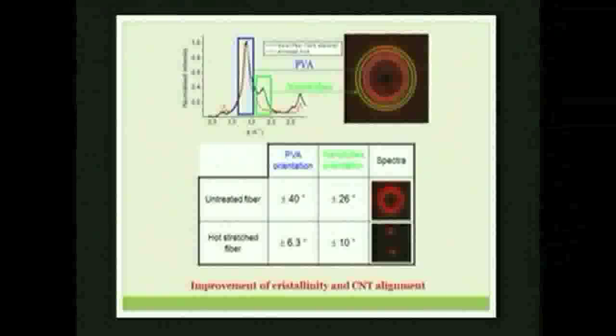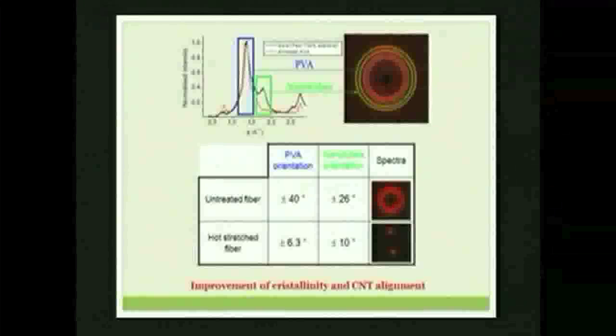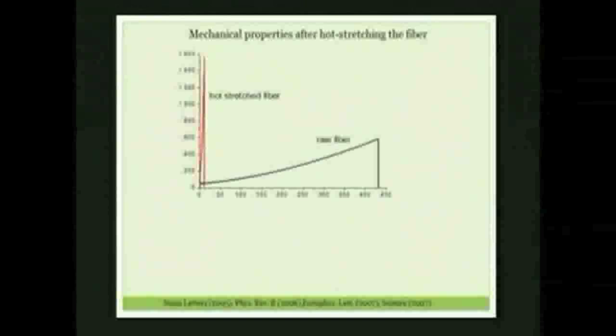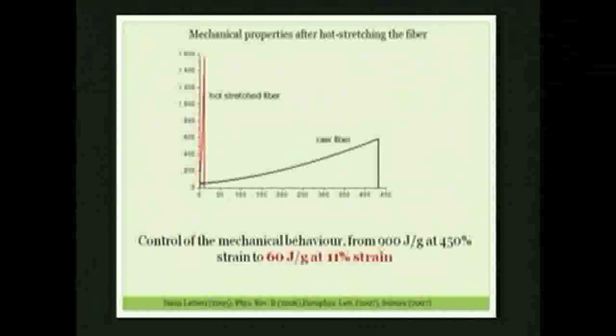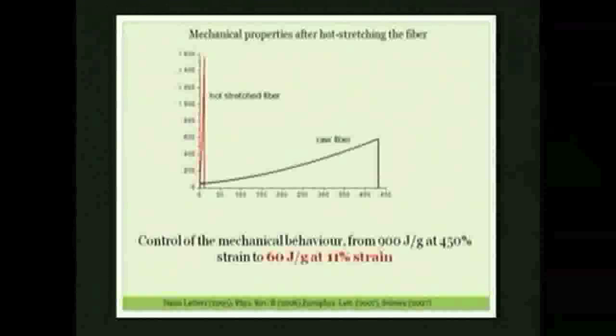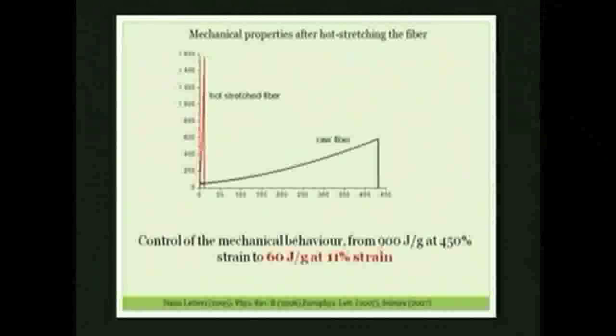And we also see that the crystallization of the polymer is improved by the heating process. And this led to completely different mechanical properties than before. This is the raw fiber that I've shown before, and this is the same fiber but after the hot treatment. And you see that the mechanical curve is absolutely different. We change the Young modulus, we change the strength, we change the deformation rate, which is much smaller now. And of course, we also decrease the energy absorption, but it's still very interesting. It's 60 joules per gram with 11% of strain. And now, this material is of great interest to make protection applications, like bulletproof vests or bumpers or whatever you can imagine.